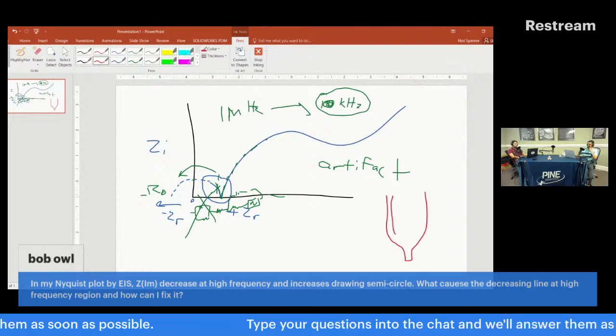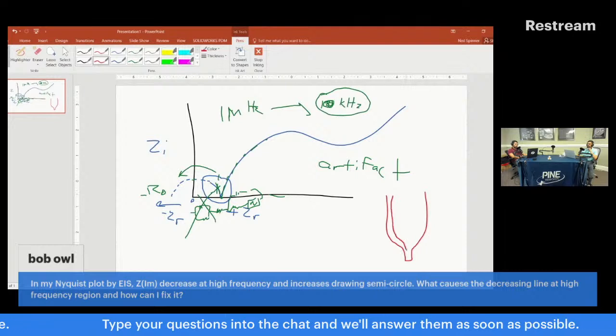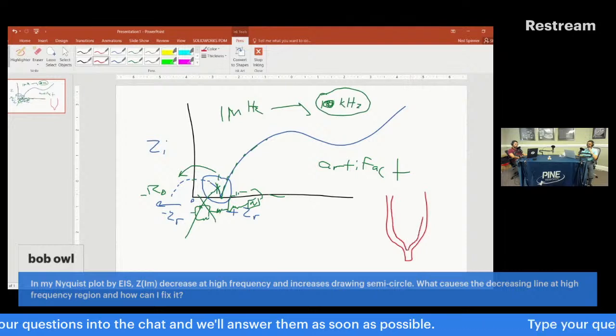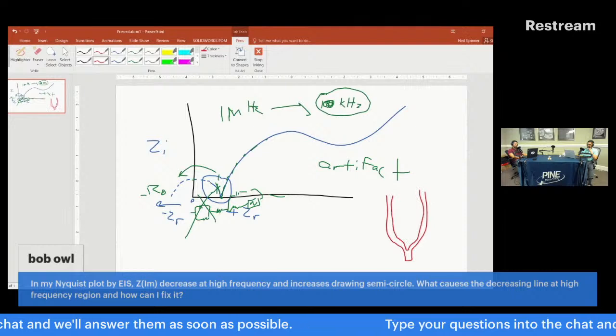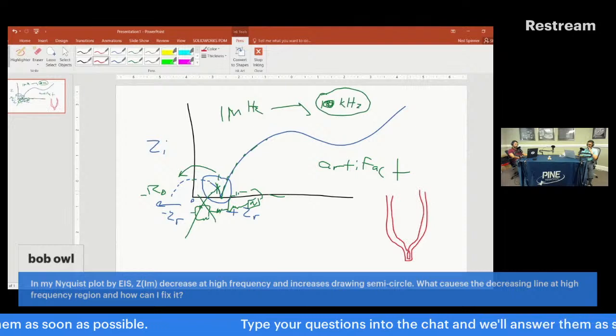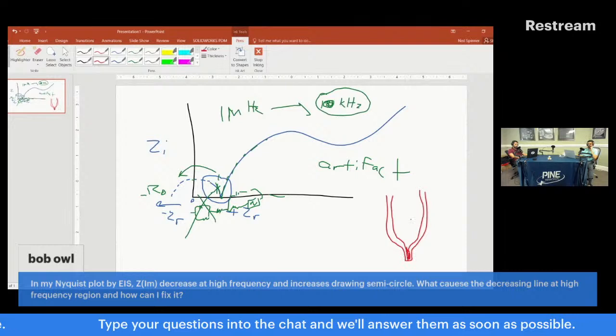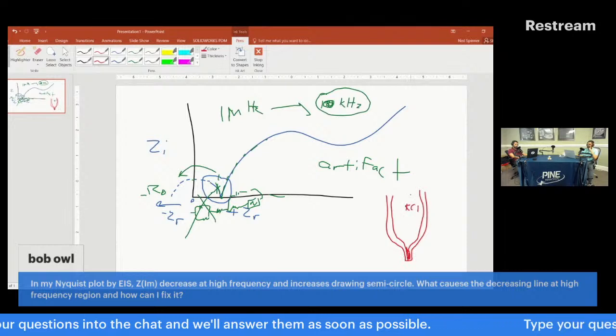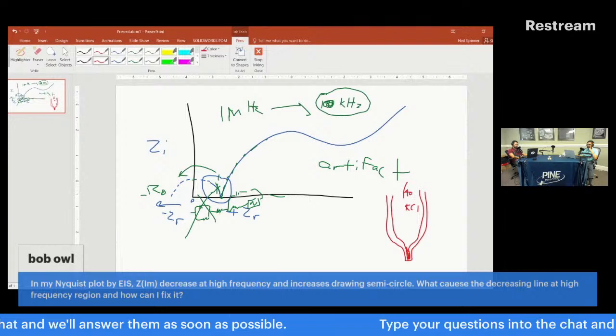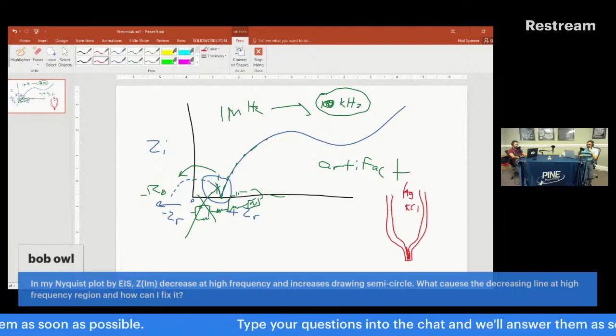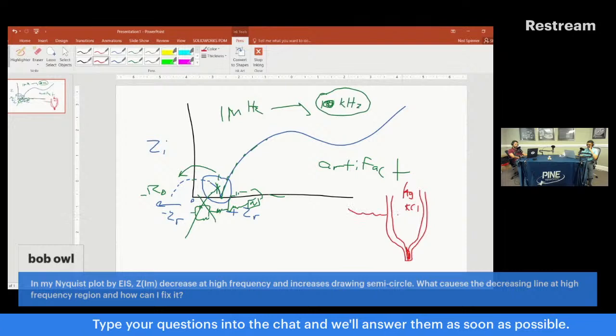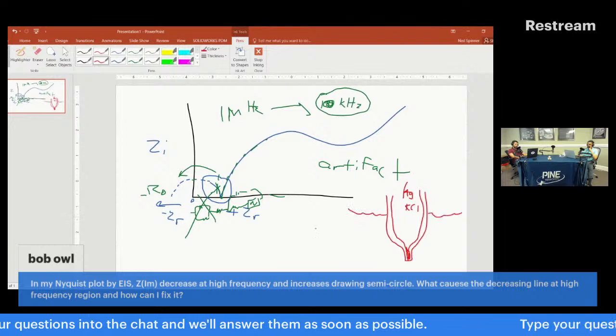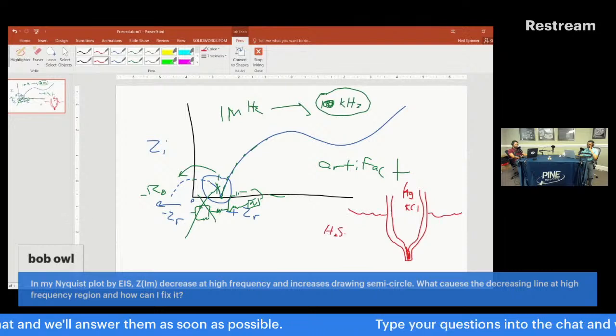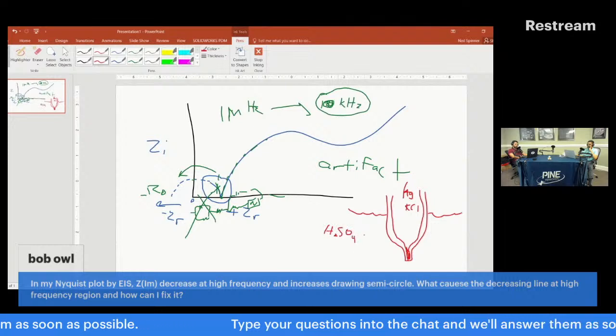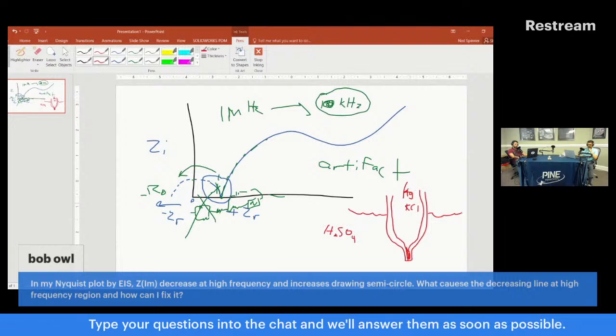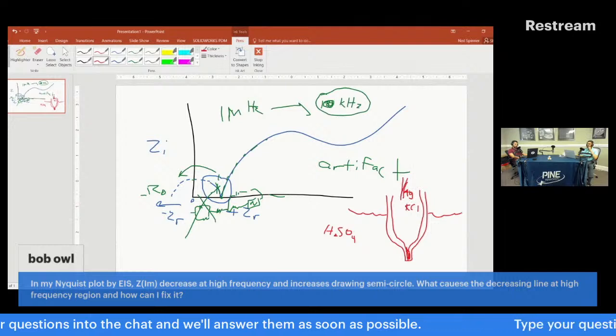So one of the things that you don't see a lot, I guess, is that manufacturers don't always give this information. But if you look up a reference electrode, typically it has this kind of format. There's a frit here at the bottom. You have KCl in here. You have an Ag wire with AgCl, and this is glass. And it's in your main electrolyte solution, whatever, H2SO4. I'm just making up stuff here. Here's your main electrolyte, here's your fill solution, and here's your silver wire. And there's a frit down here.